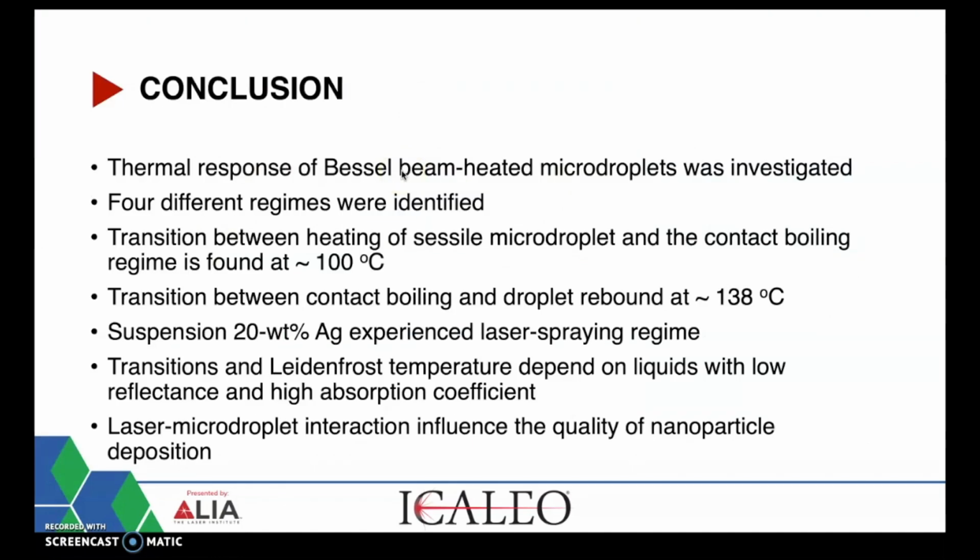First, the thermal response of Bessel beam heated microdroplets that carry semiconductor and metallic nanoparticles was investigated. Four different outcomes were identified in a phase diagram showing four regimes: heating of sessile droplet, contact boiling of microdroplet, microdroplet rebound, and laser spraying of microdroplet.